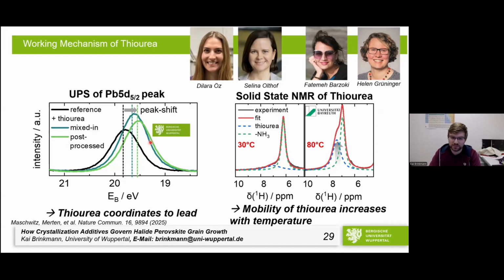And interestingly, while it sits at the grain boundary during room temperature, so you have to imagine that in the moment when we spin coat the perovskite, the thiourea is still competing somewhat with the solvent. Then we put it on a hot plate, and the solvent goes away. Then we cool it down again. Then we can measure actually. So this is the part where we can measure infrared spectroscopy, or when we can measure XPS. So this is the case that the thiourea at room temperature is actually coordinated to the lead.